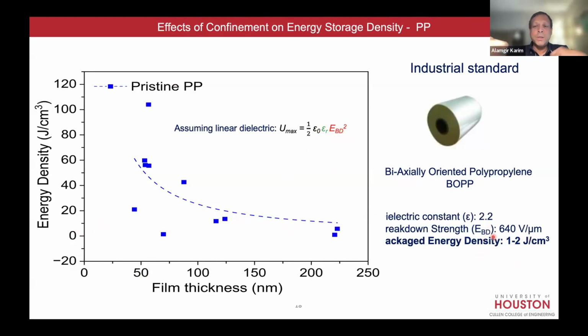But of course, we don't biaxially orient it. We could try to do that, but making ultra thin BOPP would be really difficult. But as you decrease film thickness, we're getting up to, in this one example, even up to 100 joules per cc. Let's say 50, 60 is kind of more the average realistic, but it's going up very sharply. All right. But that's still a big increase from 4 or 5, so factor of 10, like I was saying. So it would have been 200-ish if it was only breakdown, but you dropped 30% because of dielectric constant. All right. Okay.